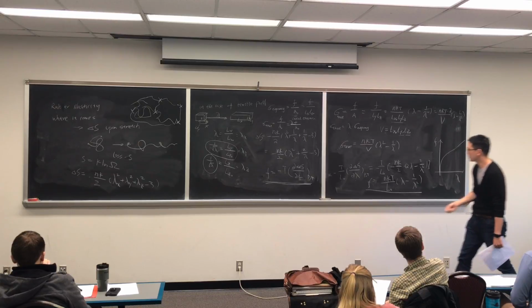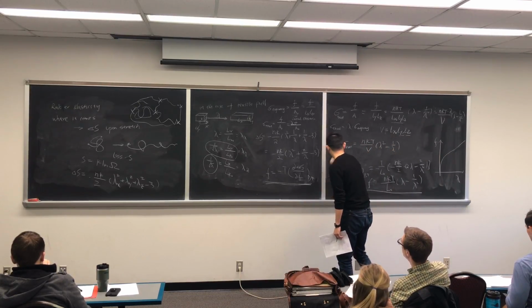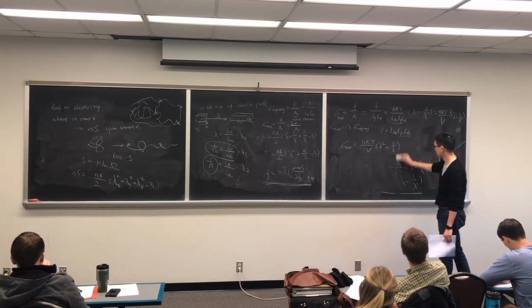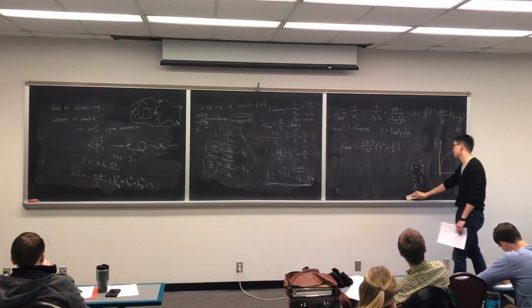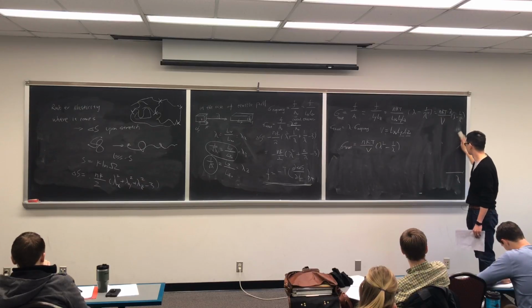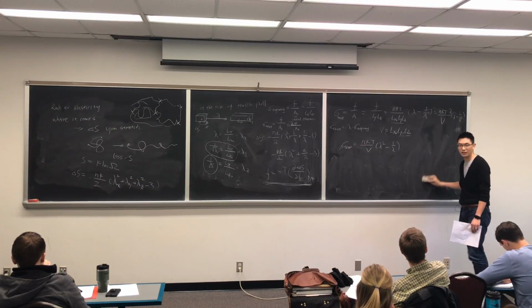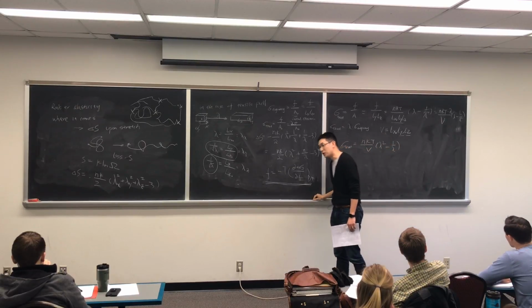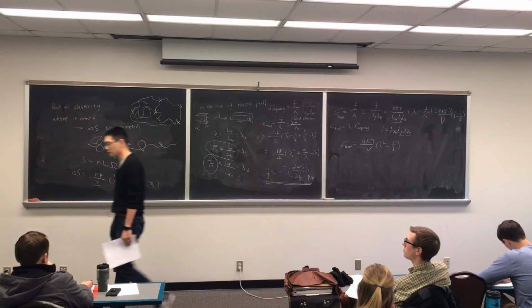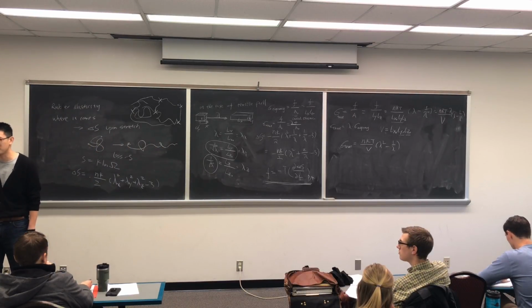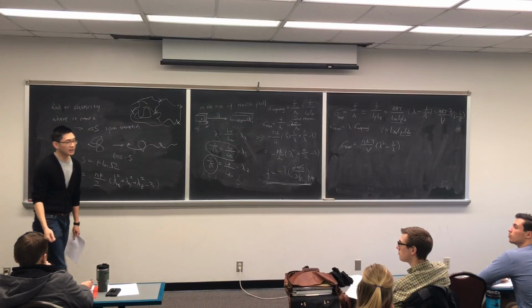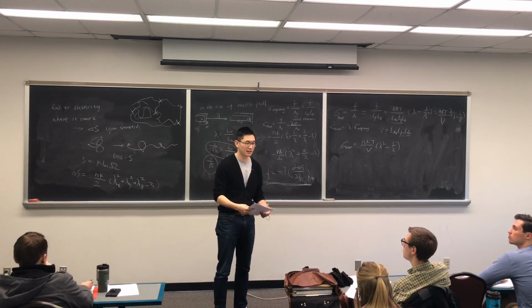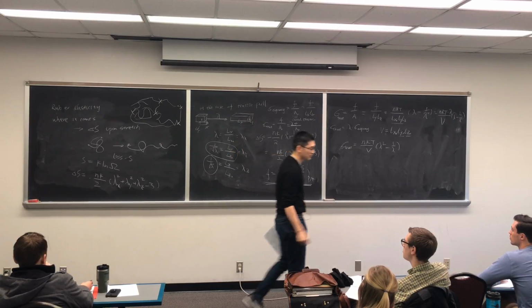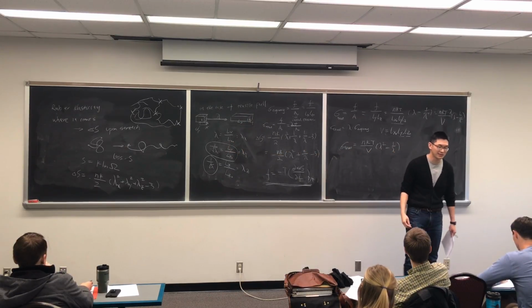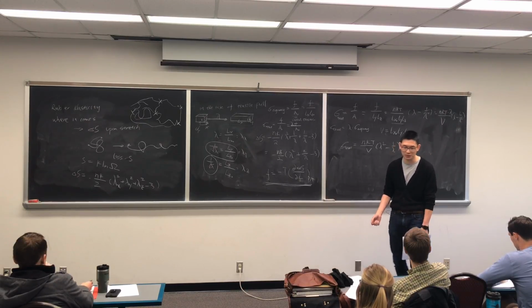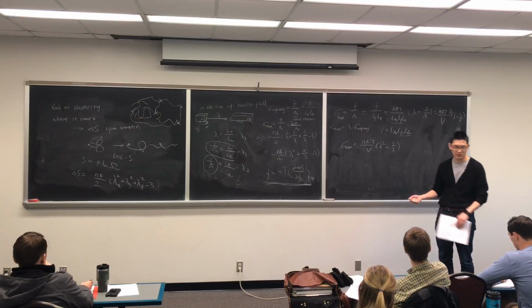And we're going to go one step further, because if you know the stress in the system, we can calculate a universal parameter for the material. That is the modulus. The modulus is one of the most important parameters for the elastomer. You know, elastomer is much softer than glassy plastics. Elastomers are typically on the order of megapascals, while the glassy polymer or structured material is on the order of gigapascals or tens of gigapascals. And you can have carbon fibers, hundreds of gigapascals, which make them really rigid.